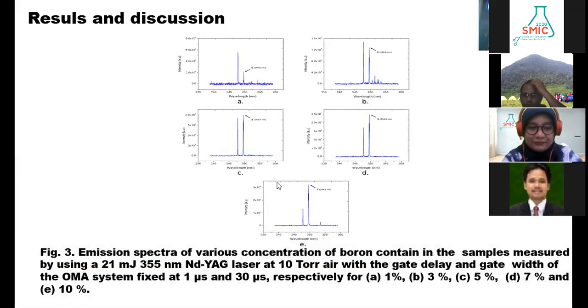The spectrum is taken by using 21 millijoule of laser energy and taken at 10 torr of air surrounding in the chamber. The gated delay and gated width of OMA system are fixed at 1 microsecond and 30 microsecond respectively. From this spectrum, we want to see the relation between the emission intensity of boron and its concentration, and the result is like that.